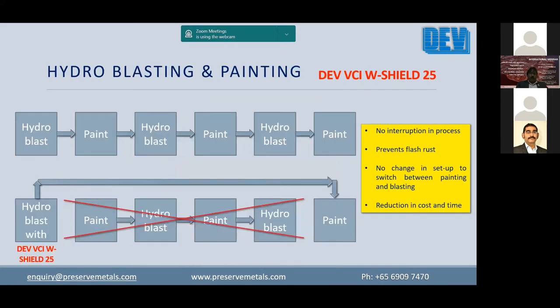And another area wherein the shipyards and the fabrication yards are currently using is the hydroblasting process to prepare the surface for painting. While doing this, one of the major problems faced by a client is that once you do the hydroblasting, you need to do the painting within about 2 hours. Otherwise, flash rust will come, and if you do the painting on top of that, the paint adhesion will be affected.